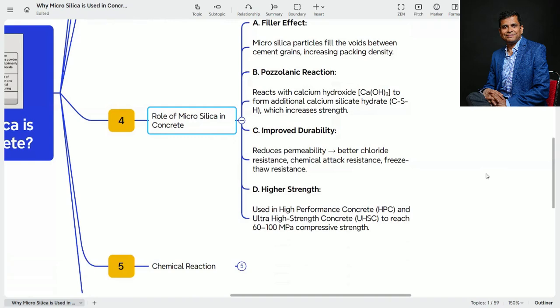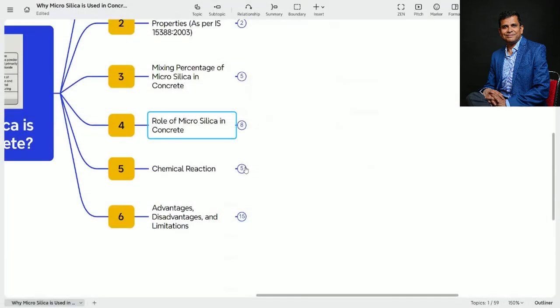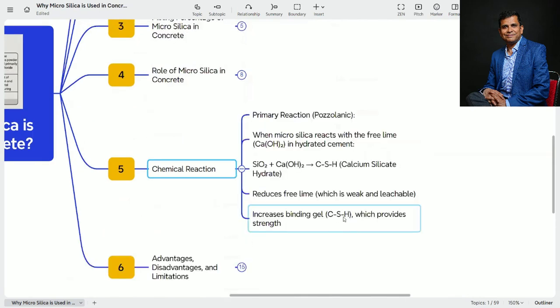So by using the microsilica, we have the effect on our chemical reaction that we already discussed. The primary reaction is the pozzolanic reaction. When microsilica reacts with the free lime, that is the calcium hydroxide, as we discussed, this free lime is produced when C3S reacts with the water. Now SiO2 plus calcium hydroxide gives CSH gel. This gel is the reason for the strength gain in concrete, the binding gel which provides the strength. So this is the chemical reaction that happens when we add microsilica into the mix.